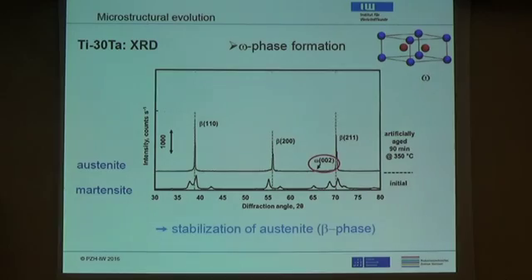So what's the reason behind that? We did some X-ray on this material. This here is the initial material. If you do X-ray, you get all those nice peaks. So it's fully martensitic. And then if you do an aging, this here is at 350 degrees C, you don't even have to cycle it. If you do X-ray after this aging, all the martensite is gone.